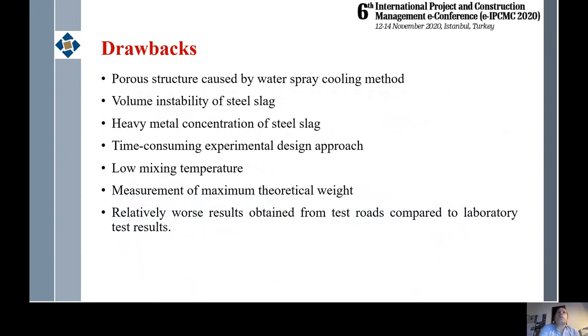And from the experimental period and also the test roads, we have some drawbacks, and these are noted as you can see here. Porous structure caused by water spray cooling methods, which affects the water absorption value of steel slag, and the water absorption value is generally higher than the conventional aggregate. Volume instability of steel slag, heavy metal concentration of steel slag, time-consuming experimental design approach, low mixing temperature, measurement of maximum theoretical weight, relatively worse results obtained from test roads compared to laboratory test results.